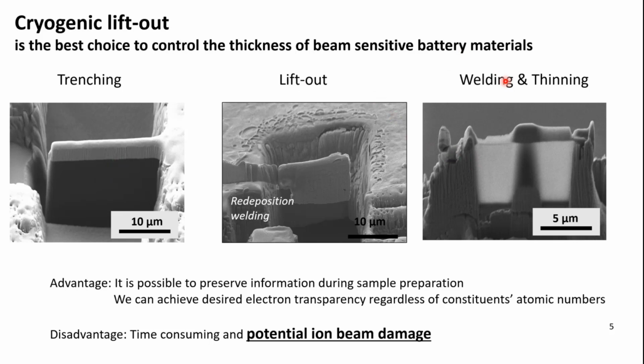There are a few important advantages in using this technique. First of all, we can preserve as much information as possible when you prepare battery materials. And secondly, you can have the desired electron transparency regardless of the atomic numbers of your systems and the original thickness of your samples. However, there are still limitations in this method. First of all, it is pretty time-consuming to make one single sample, and there still exist concerns about ion beam damage.